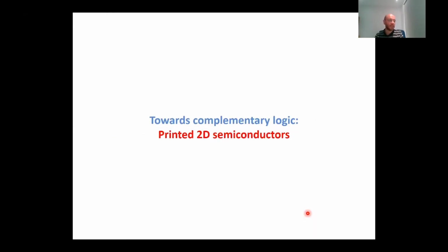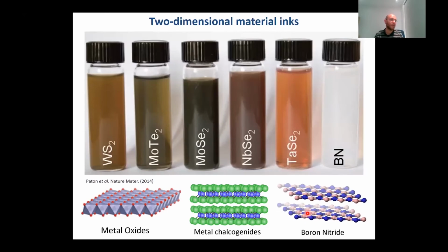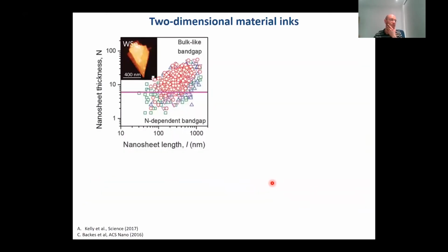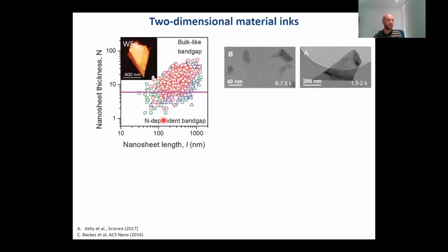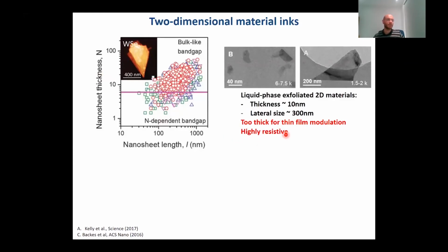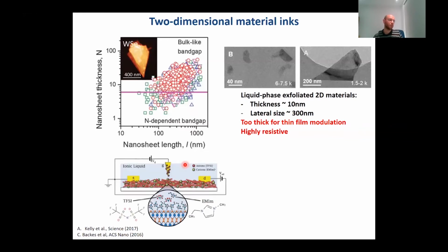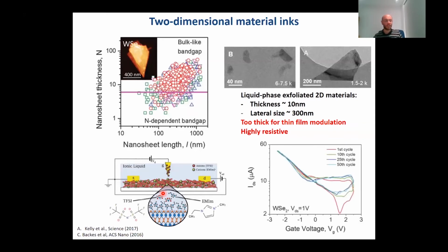So we start looking at other two-dimensional materials. As we know, there is a large range of two-dimensional materials, and these can be exfoliated by LPE. But the problem here is that the thickness is very high. So you really can't get nice devices that can be nicely modulated. They are too thick, they are highly resistive, and there are a lot of reports that have shown that the only way to get some modulation is by ionic liquid gate modulation. So that's not really good. You get a kind of electrochemical cell, which is not even stable.